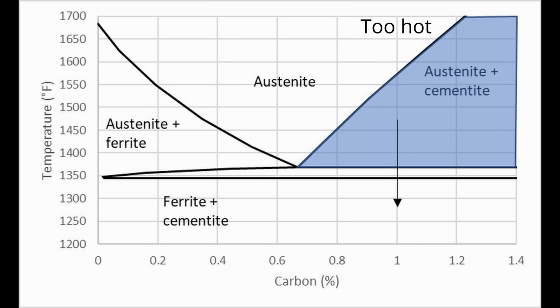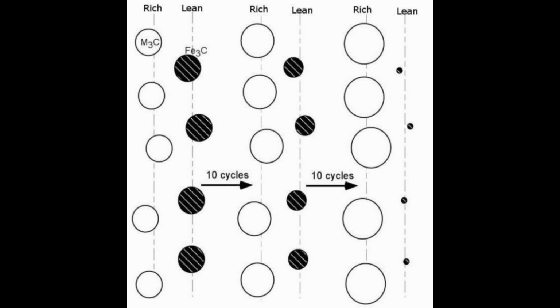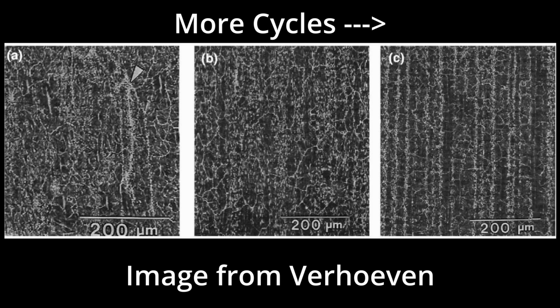If you overheat the steel, all of the carbides dissolve, and then they re-precipitate or reform throughout the steel relatively evenly. But if you don't dissolve the carbides, if you heat up to an intermediate temperature during the thermal cycling or forging process, the carbides will coarsen in the areas that are high in the carbide former. In this case, niobium, but it could be vanadium or chromium or even manganese. In those rich areas, the carbides will coarsen, and in the carbide-former-lean regions, the carbides will shrink during the thermal cycling process.